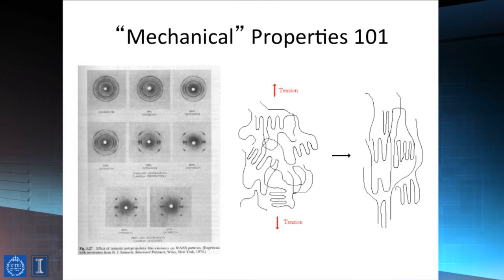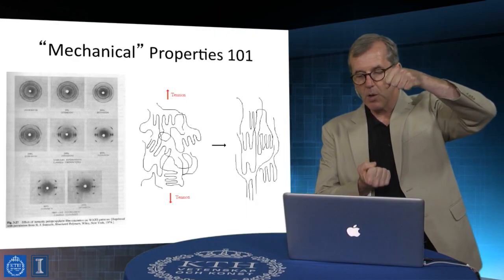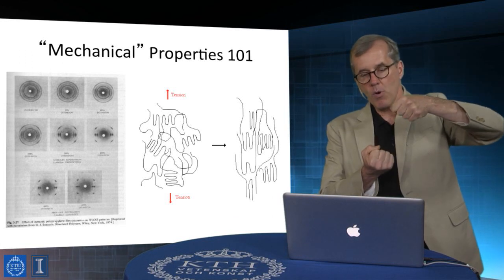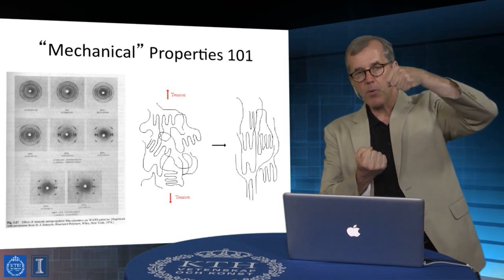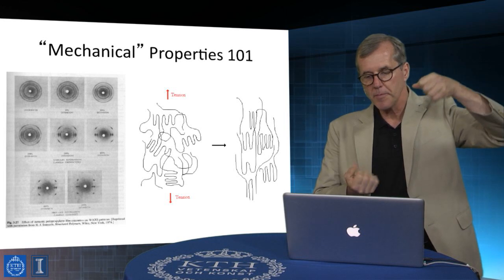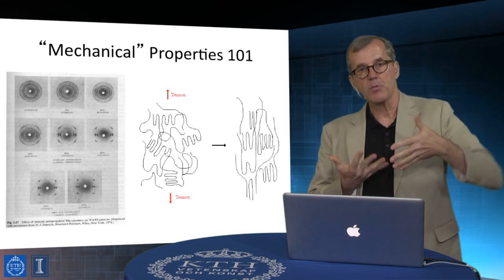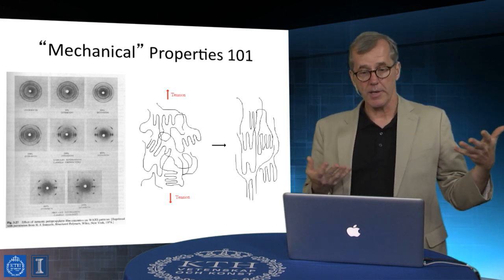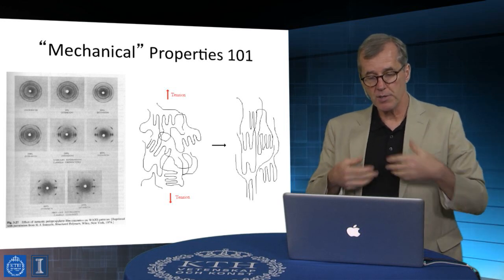And basically, what's being done is a polymer is being put into a tensile strain. It's being elongated. And as it's being drawn, right, we're not drawing it to the point where it actually breaks. As it's being drawn, the chains within it are actually reorganizing, and the chain structure is evolving.